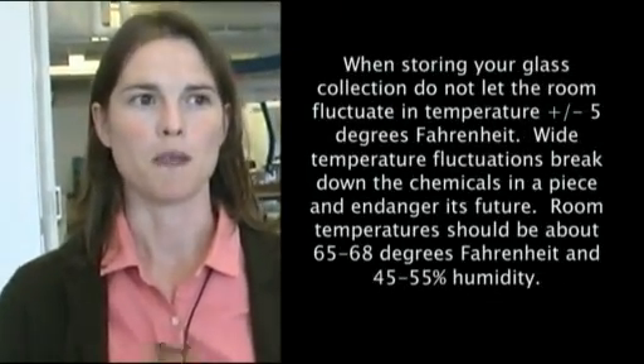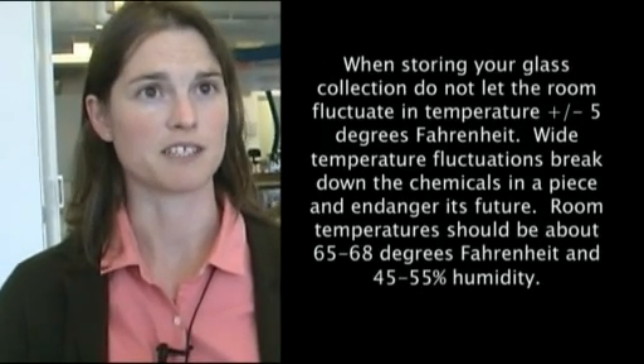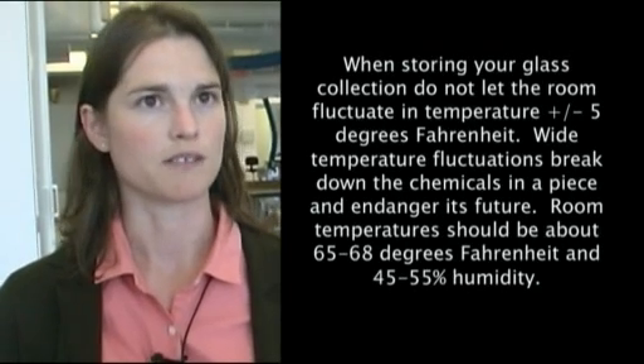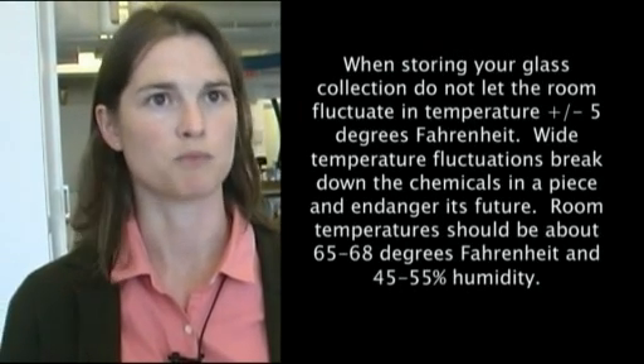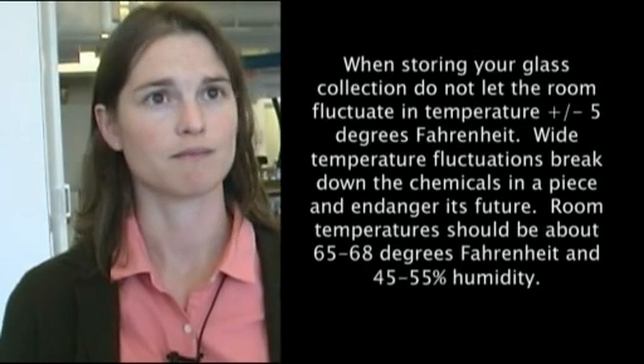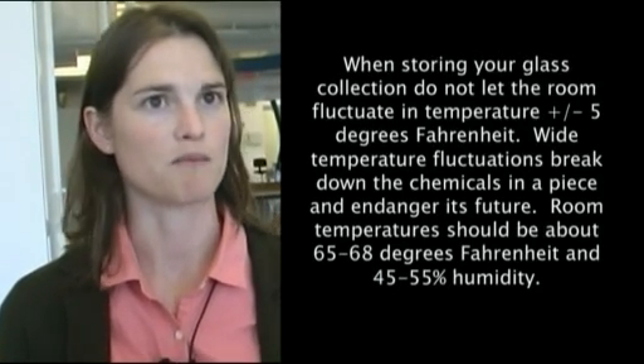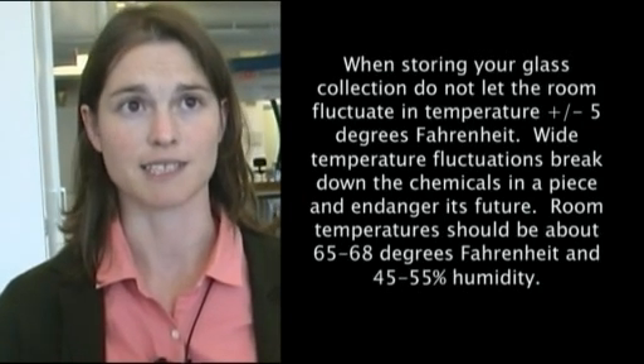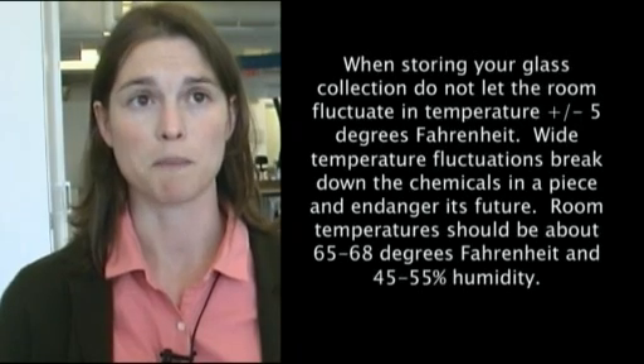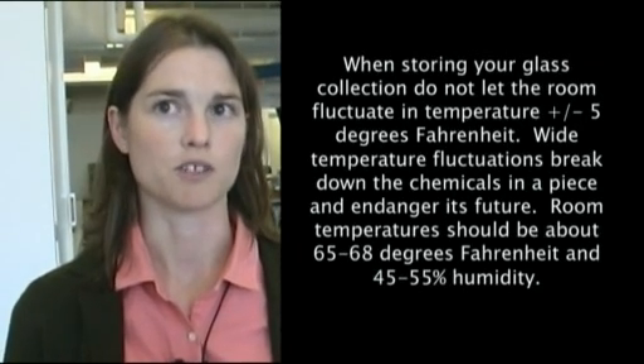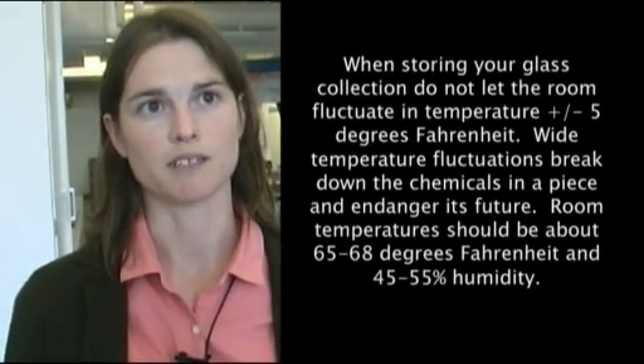For somebody who's a collector, what you want to make sure you do is have a stable environment for your collection to be in. You want a temperature in the range of around 68 degrees Fahrenheit, plus or minus 5 degrees. Relative humidity you'd want to have pretty stable, around 45% relative humidity, give or take 5%, even up to 55, 60. Any higher than that, you have the danger of weeping, which is a condition that occurs when you have too much humidity, and you get kind of a soapy feel on the surface of your glass. Or if it's too dry, you end up with crizzling. And both of these are irreversible products of having an unstable environment.